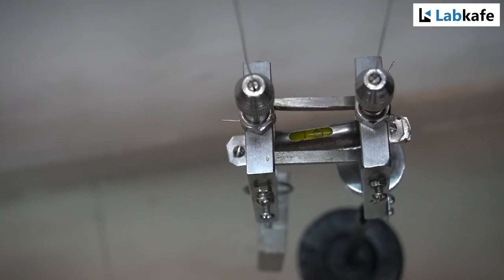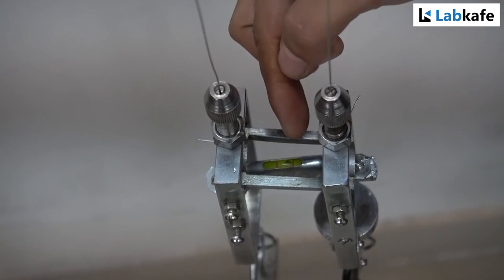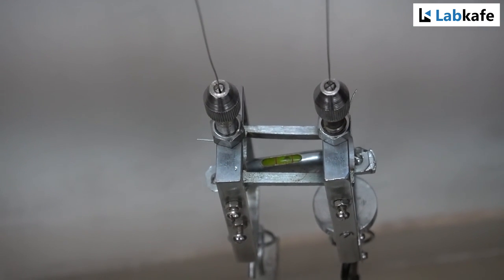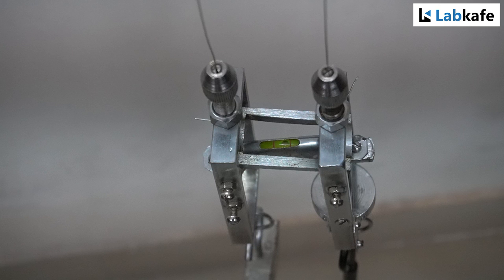Because the steel wire is very strong, by loading, the elongation may not be very large. Therefore, to observe the little movement of the bubble, it is a good practice to keep the bubble just to touch the reference line. Otherwise, it is difficult to observe the elongation if you keep the bubble in the middle between the reference lines. At this stage, we say that our setup is at zero load condition.